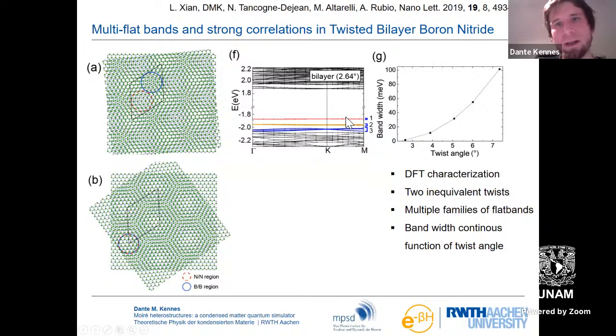Now we can, of course, look at the bandwidth of this band labeled one in dependency of the twist angle. And we see a nice monotonic curve. As you go to smaller twist angle, the bandwidth of this red band monotonically decreases. So this means that we can use twisting as a way of controlling the overall bandwidth, the kinetic energy scales in the system. For the experts on twisted materials here, this is another fundamental difference to the bilayer graphene case.